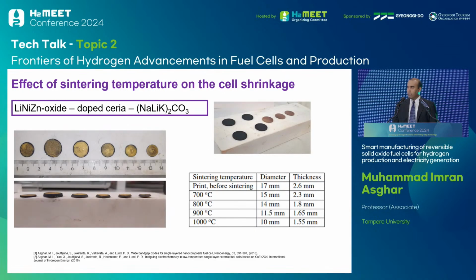So after printing, we do the sintering step. Since the single layer has to function as an electrolyte and also as an electrode, we have to find the right porosity, because if the cells are very dense, then the electrode processes suffer. Similarly, if the cells are very porous, then there is a danger that the gases can cross over. So we do a systematic study to find the right densification.